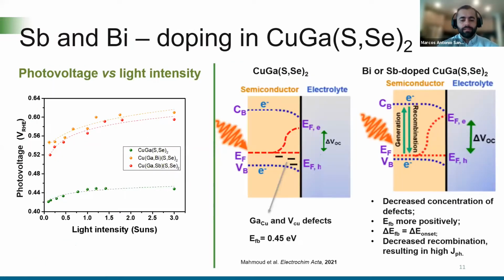To understand why bismuth and antimony doping promoted the high photocurrents, we plotted the photovoltage that we obtained by JV curves versus the light intensity. We know that the higher the light intensity, the higher is the photovoltage. But because of the larger concentration of defects in copper gallium sulfoselenide, there are these mid-gap states that become more populated with increase in the light intensity, not allowing the photovoltage to further increase, and instead cause the quasi-Fermi level pinning.